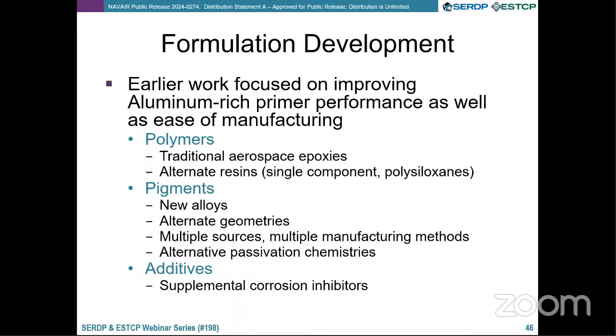In addition to that, there are lots of theories in terms of what makes a metal-filled coating effective electrochemistry. People have studied this for a number of decades, and what pops up is under things called percolation theory, the idea that surface area of the particle, as well as contact of the particles between each other, is really important to have higher or lower degrees of electrochemical action or spread throughout the coating, where it is contacting either a different alloy like a fastener or a defect like a scribe through the coating.